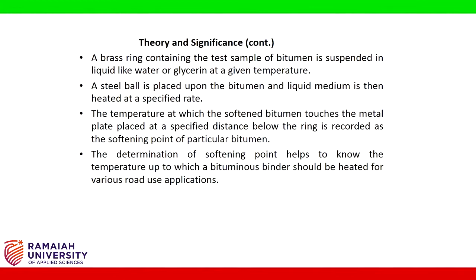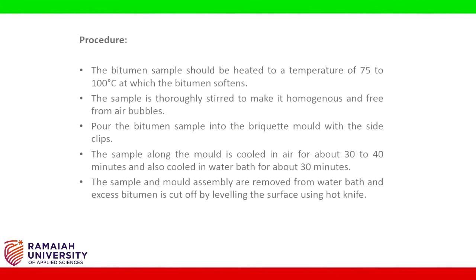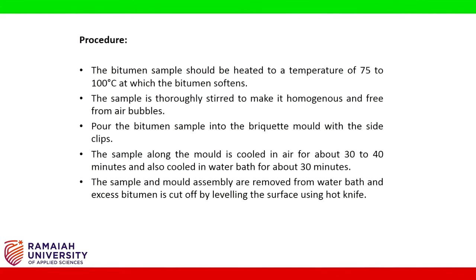The temperature at which the softened bitumen touches the metal plate placed at a specified distance below the ring is recorded as the softening point of that particular bitumen. The determination of softening point helps to know the temperature up to which a bituminous binder should be heated for various road use applications.